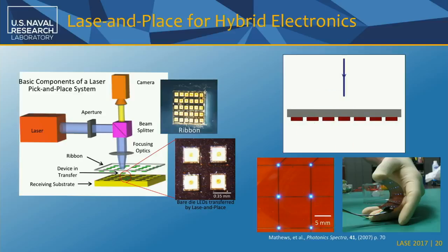And instead of having an ink, what we have is a donor substrate, a transparent plate, with devices that are attached using a polymer layer. The polymer works beautifully because it absorbs the laser, vaporizes, and that vapor pushes the device forward. And in the process, we do not damage the device. I like to point out that we are transferring these devices with the pattern side facing up, facing the laser.